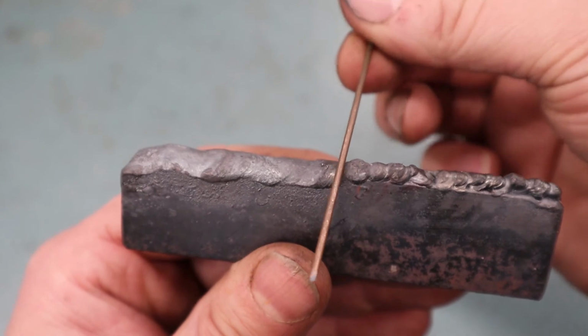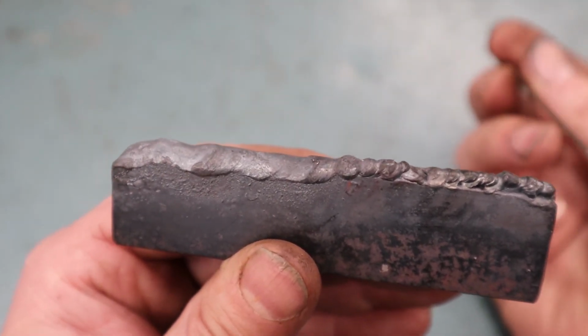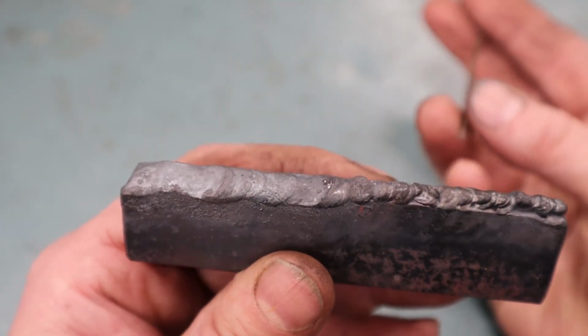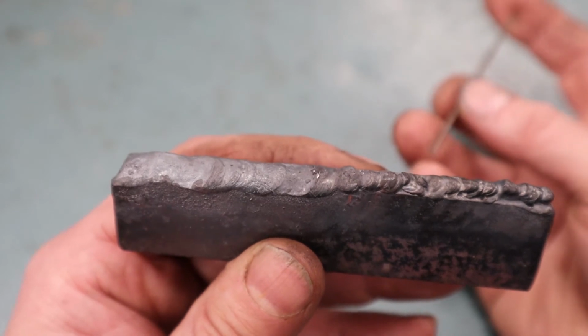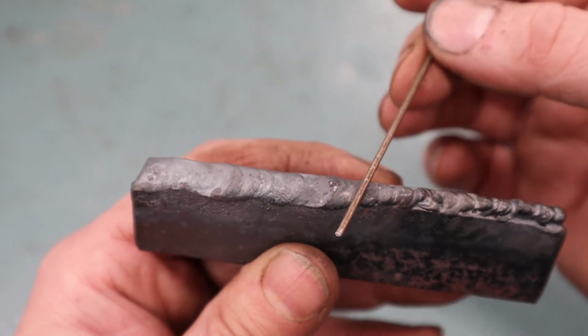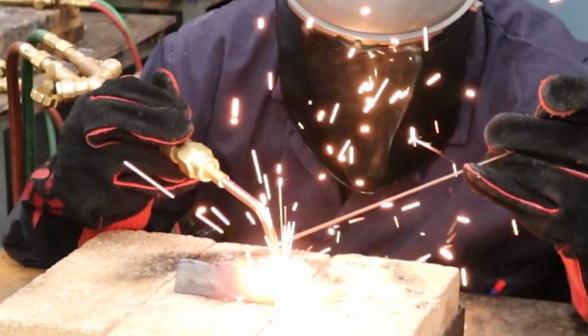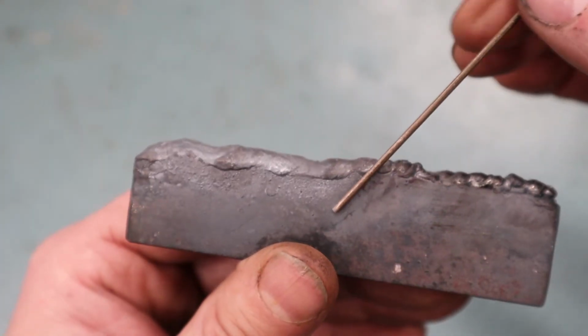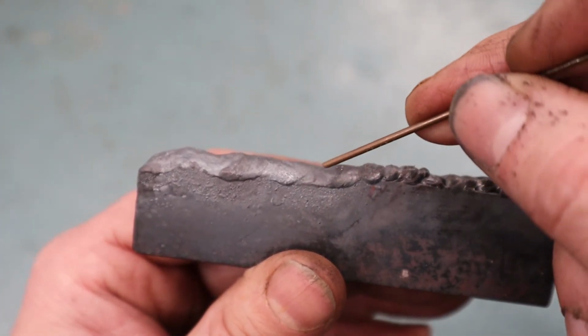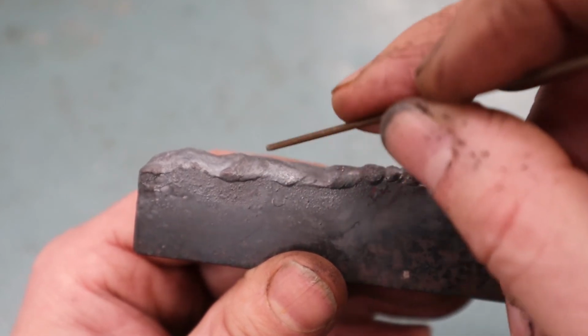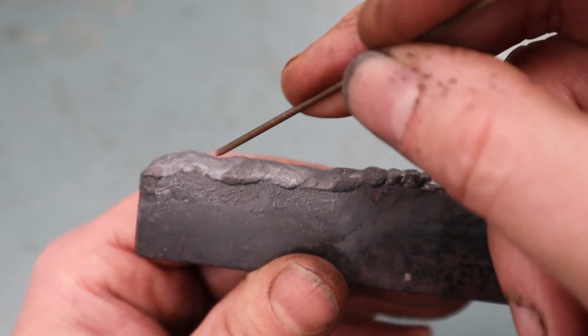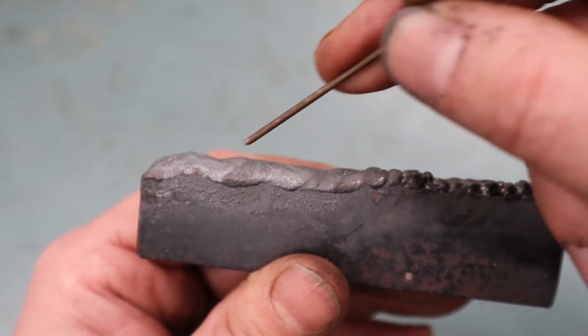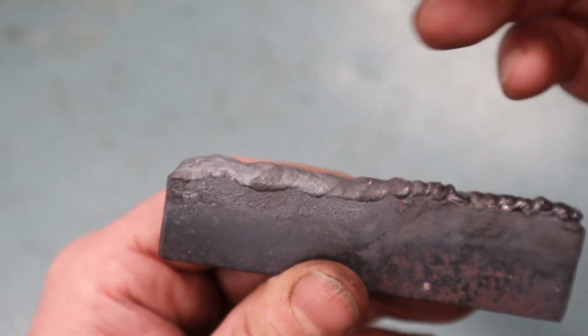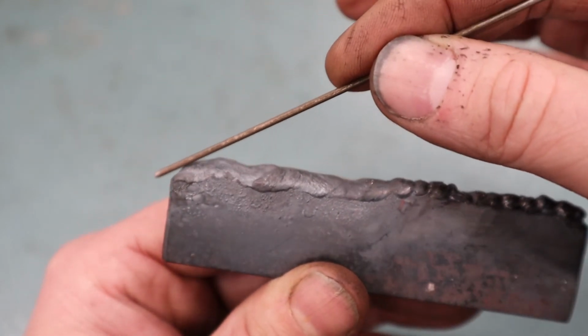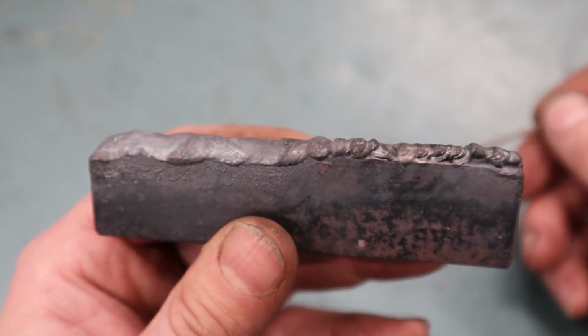Now this side is really too hot, and you can tell first off because it's got a dry gray, ashy look to it. It looks burnt, and when I was doing that, there were lots of little twinkle sparkles coming off of it. And the other clue is there is not a lot of overlap. There's actually some undercutting happening where the puddle is robbing the base metal to put it towards the center to try to make a bead for you. At the very end, you can see lots of heat melted the corner off as well. So too hot and too cold.